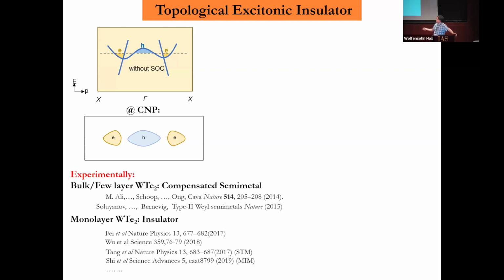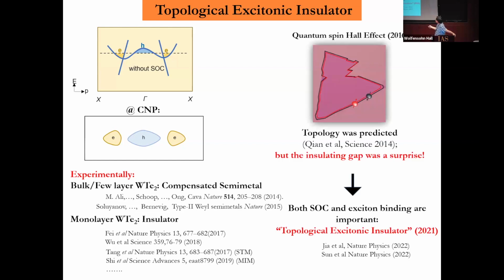What's really surprising is that the monolayer, if you exfoliate down to monolayer, is actually insulating. This was the very first surprise we had, because we saw semimetal in bulk - band structure calculations and properties of the bulk are all semimetal. We thought we'd exfoliate, get a monolayer, and have a semimetal to study. But at the end, we found an insulator. So this was one of the big surprises in the beginning.